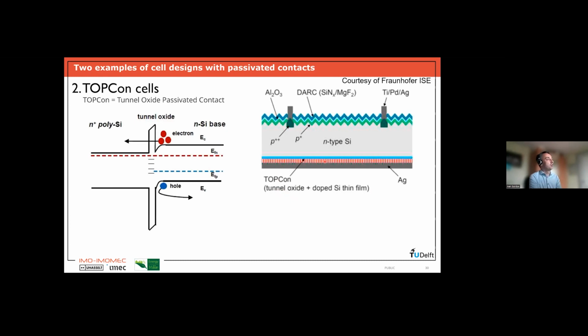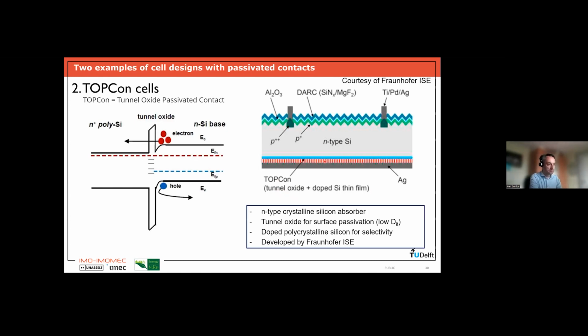And this is also an example of a passivated contact, which is carrier selective. So the tunnel oxide is typically used for surface passivation, so to reduce the dangling bonds at the surface. And the doped polycrystalline silicon layer is then used for selectivity. It was originally developed by Fraunhofer ISE, this cell concept, but of course many companies and many institutes have also made variations of this.